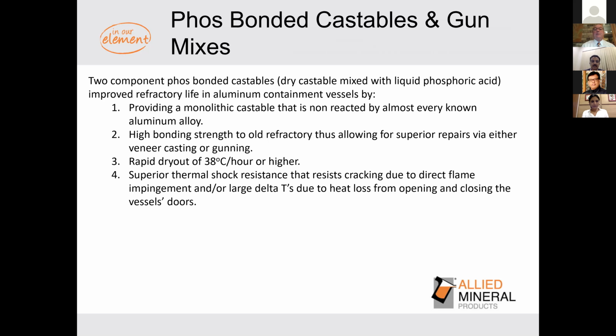Again, the 2-component phos bonded castables, where you have the dry material and the liquid phosphoric acid, was a monumental improvement in refractory life in aluminum furnaces and all containment vessels, dosing furnaces, launders. All of these, life was dramatically improved. Easier cleaning when we went to the liquid phosphoric acid systems. I have done extensive testing over the last 40 years. I've tested literally hundreds of refractories from around the world in contact with various aluminum alloys and salt fluxes. And I have found that the phosphoric bonded materials have resisted every alloy that I have tested them against. It's, again, an outstanding technology.